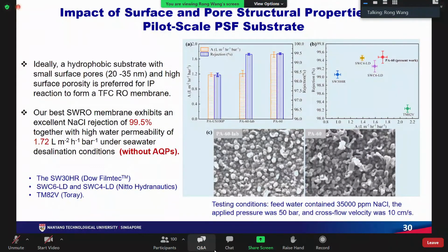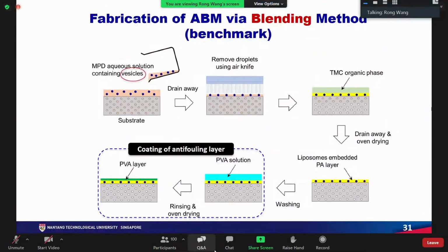Through this substrate optimization, we get the best SWRO membranes that have a sodium chloride rejection over 99.5%, and the water permeability is 1.72 LMH per bar under the seawater desalination condition. Here, I would like to draw attention: without aquaporin incorporation, we just optimize the substrate. We compared our membranes with the commercial membranes in the chart. You can see our membranes show pretty good performance.